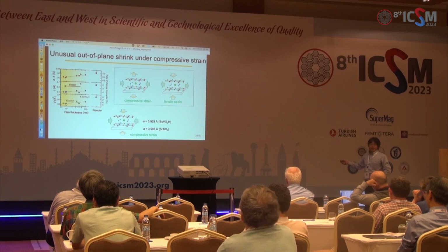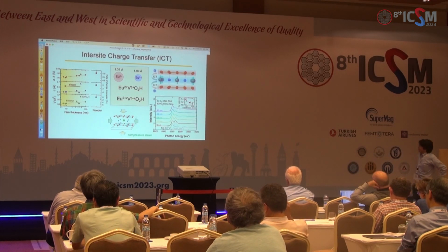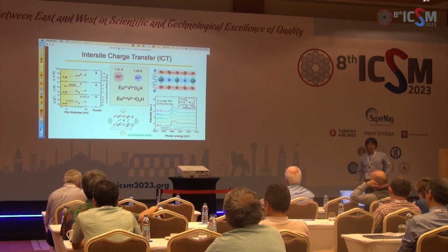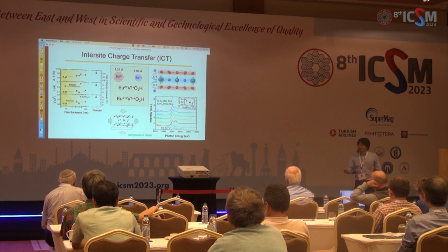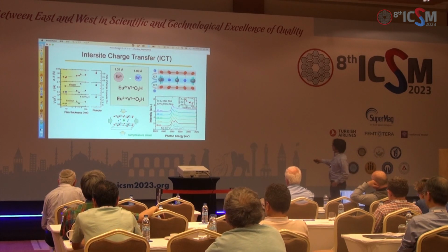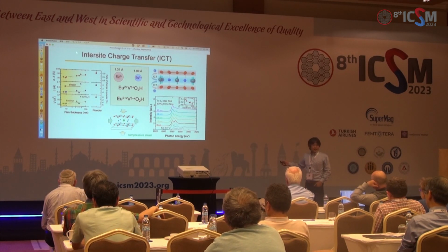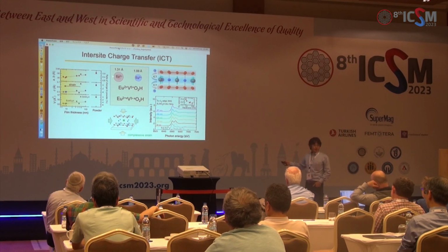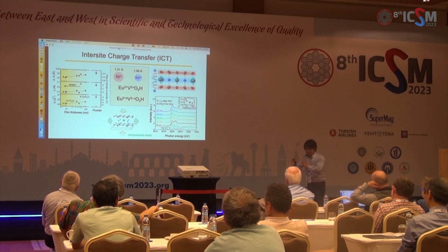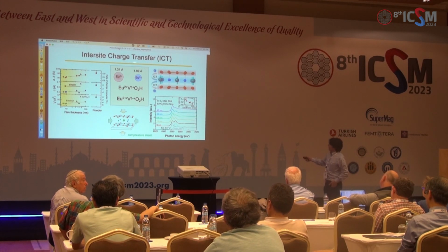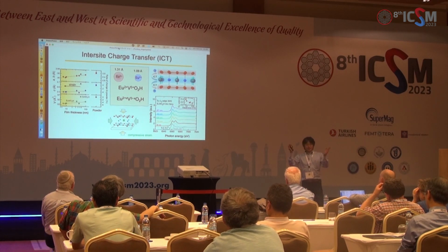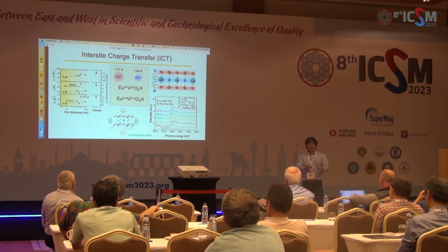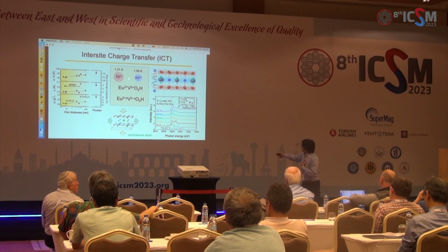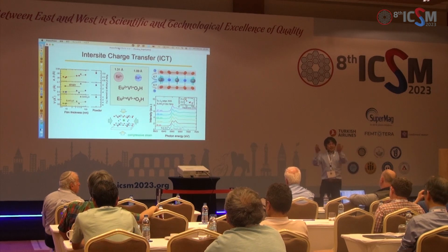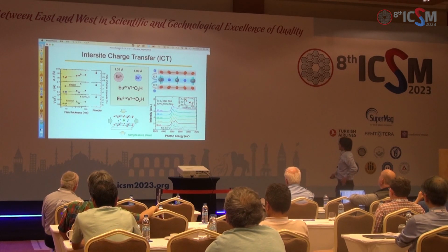So this is unusual. Then we speculate that charge transfer should occur in this material, in the thin film. In the case of Eu2+, the radius is something like 1.31 angstroms, while Eu3+, with higher charge, of course has a smaller radius, 1.09. So we observed that by applying the compressive strain, the volume was actually reduced. So maybe some of the Eu becomes oxidized. So this is our speculation.